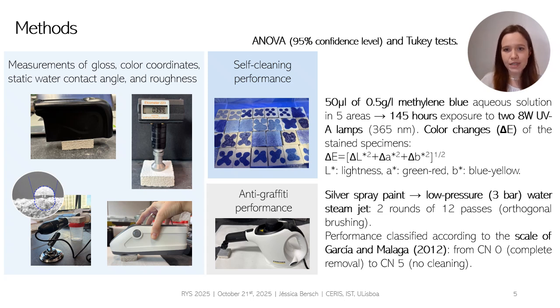For self-cleaning performance, we applied 5 stains of a methylene blue aqueous solution on each specimen. Then, the specimens were exposed to 145 hours of UV light. Color changes of the stained specimens were monitored throughout time and compared using CIELab color space. For anti-graffiti performance, we applied a silver spray paint over the specimens. Then, removal was attempted with a low-pressure water steam jet in 2 rounds of 12 passes. The cleaning performance was classified according to an existing scale from complete removal to no cleaning.